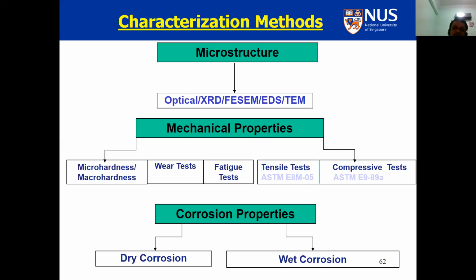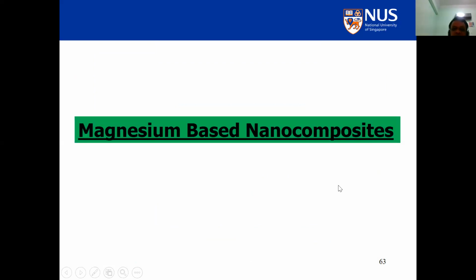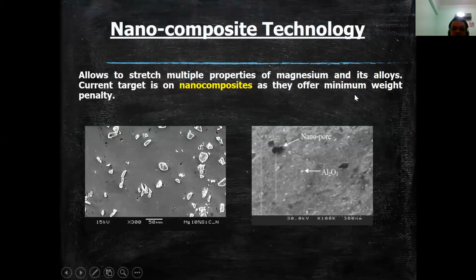So you have to characterize your material from a microstructure perspective, from a mechanical perspective, and also from the corrosion perspective. So we focus on nanocomposites. In the nanocomposite, you disperse nano-sized reinforcement like the one you see on the right-hand side, Al2O3 particles there. And on the left-hand side, you see the micron-sized particle. What is the difference? The size of the particle. We try to go for the nano size particle, and we call that a nanocomposite.